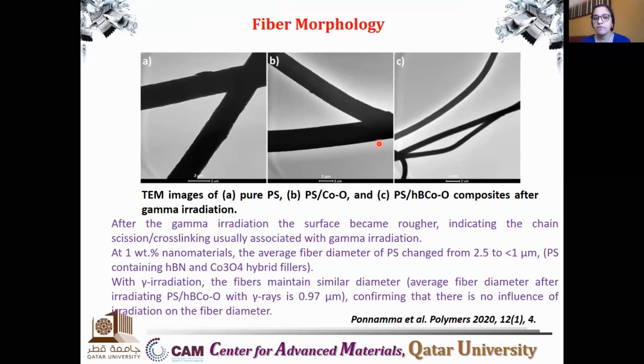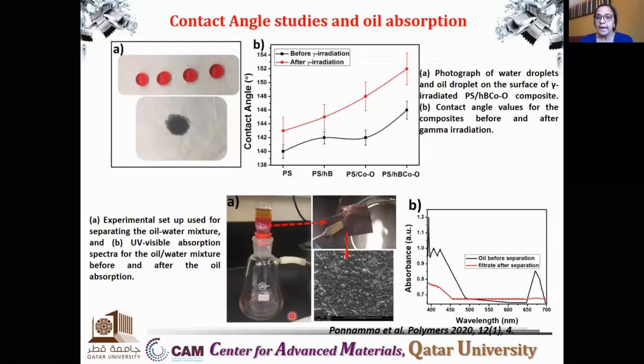And we found that with gamma irradiation, the fibers maintain a similar average diameter, confirming that there is no influence of irradiation on the fiber diameter. So the irradiation is not affecting the electrospinning or the fiber diameter. Rather, it is only affecting the crosslink density, or the compatibility between the filler and the polymer molecules. And in line with the previous research, this is the water molecules standing on the top of the fiber. Again, the fiber was super hydrophobic. And again, after gamma irradiation, we got good results.